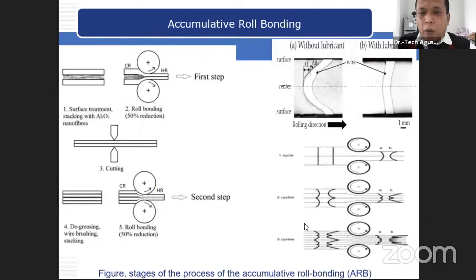So for accumulative roll bonding, it is a type of severe plastic deformation process where rolling a stack of sheet material is used to refine the grain size. Generally, nanometer or micrometer grains have higher strength than conventional material that has grain size larger than a few tens of micrometers. So for the stack of material, we use some parts of material and cut them into different pieces, so we can get accumulative roll bonding.